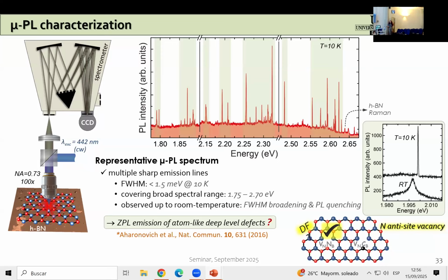But we recently performed a DFT calculation. I think the T is missing here, so sorry for that. Which basically shows that the defect that is giving such sharp emission lines is most probably the nitrogen anti-site vacancy. And this is also reported by some other authors who performed similar research, and they also came to a similar conclusion that the actual atomic defect that emits single photons in the hBN system is the nitrogen anti-site vacancy.